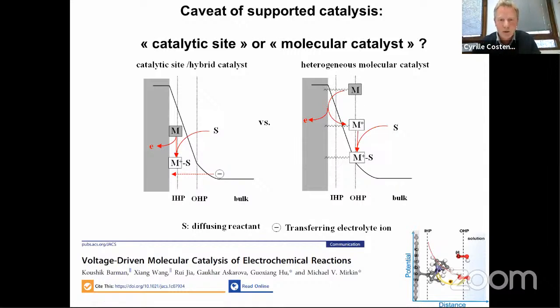And I just want to mention here a paper that just came out in JACS a few days ago by Michael Mirkin, showing exactly this effect, where you can have, even if you attach the catalyst in a way that its electronic states are not conjugated with the conductor, if the distance between the electrode surface and the catalyst is small enough, the molecular catalysis process will be driven also by the change of potential across the double layer, okay? So I would say that when you have a supported catalyst, okay, you really have to take care of whether you are in this situation or this one or in between, okay?